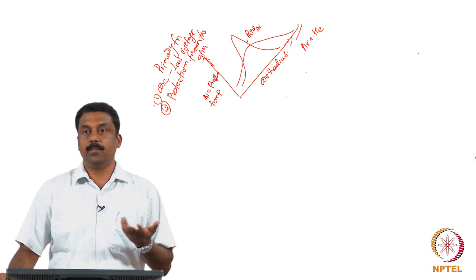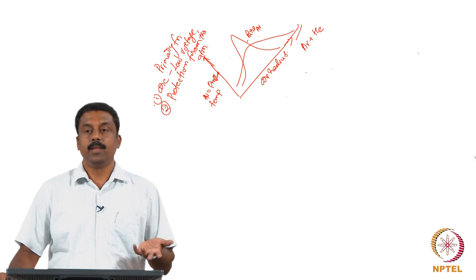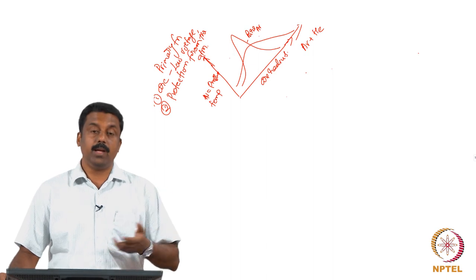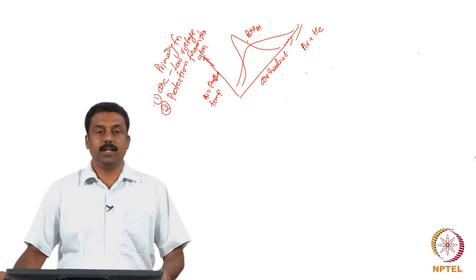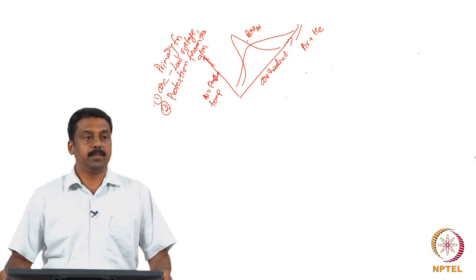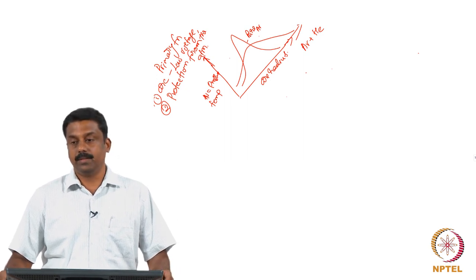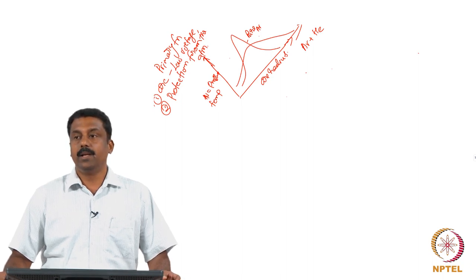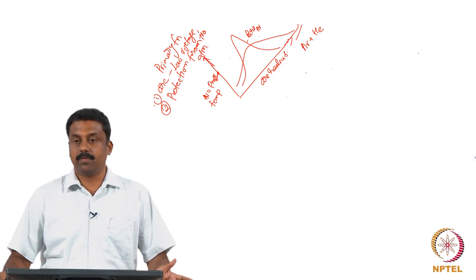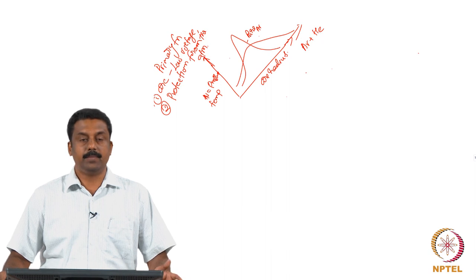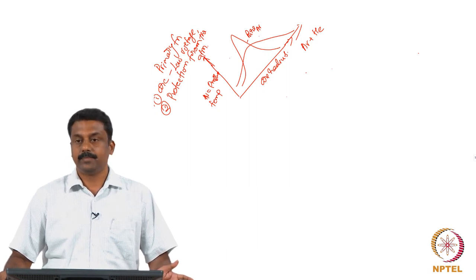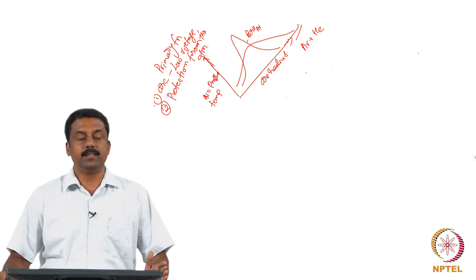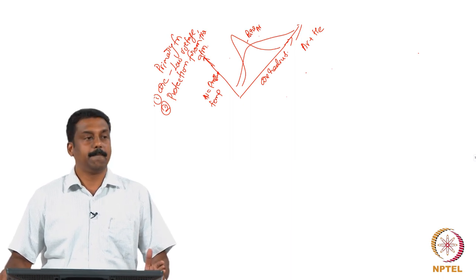Some gases can also be reactive - for example carbon dioxide. CO2 dissociates to form carbon monoxide and oxygen, and you may also end up with some carbon pick-up in the base material, changing its composition. The same goes with oxygen: if you use oxygen in a shielding gas, it can get dissolved in the base material, leading to non-metallic inclusion formation. If you have highly reactive elements like aluminium in the base material, aluminium readily reacts with oxygen and is eaten away as aluminium oxide slag.